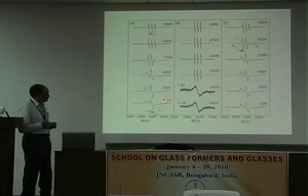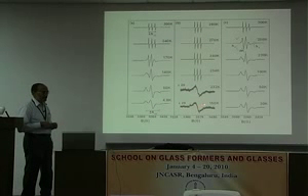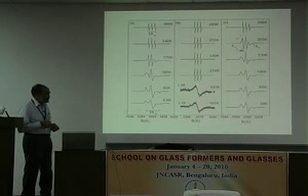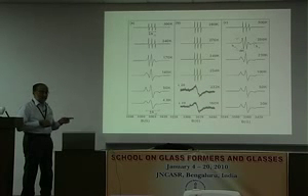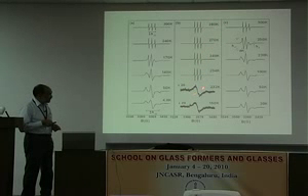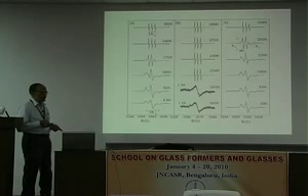This is for a quenched sample. This one is for a slowly cooled sample where there is no chance of vitrified water happening. So, here you see one single signal which I showed you earlier as a signature of crystalline samples. So, slowly cooled water ends up in a crystal, a fast quenched sample gives you vitrified water.